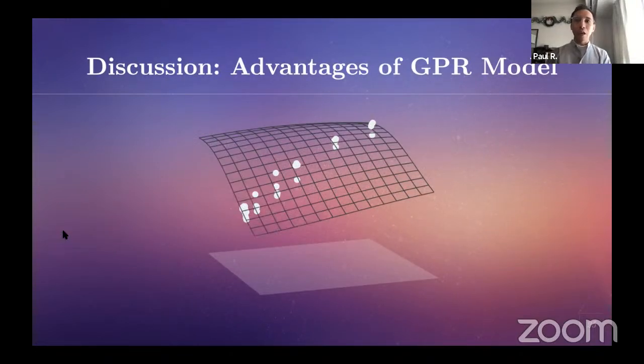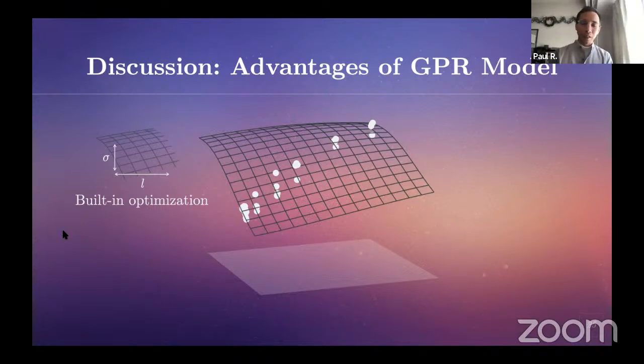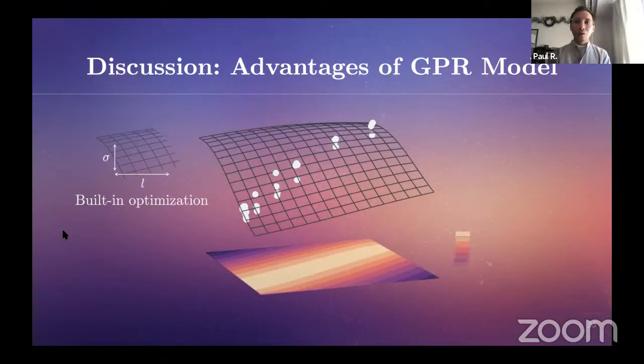Finally, let's discuss the advantages and disadvantages of using our GPR model. First, GPR has a built-in hyperparameter optimization via the maximization of log marginal likelihood, and this makes the model consistent and robust even without the need for cross-validation. Second, since the model is probabilistic, we can see the confidence level of the model on its predictions. For example, here, the model has high confidence on predicting samples along the yellow band, which is where our current data samples are in. As we try to predict other samples farther from the center, the model becomes less confident.